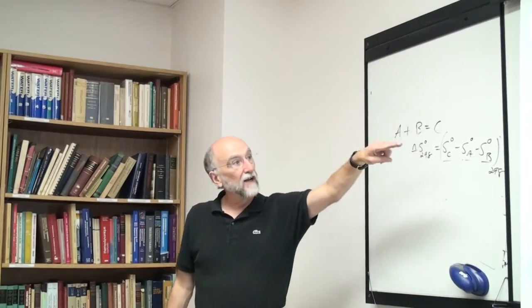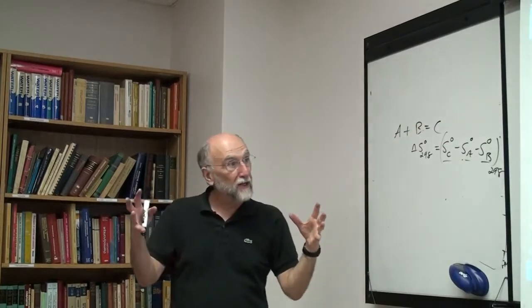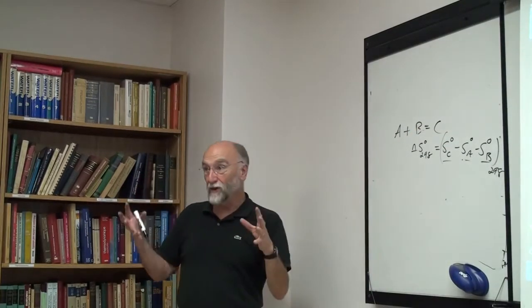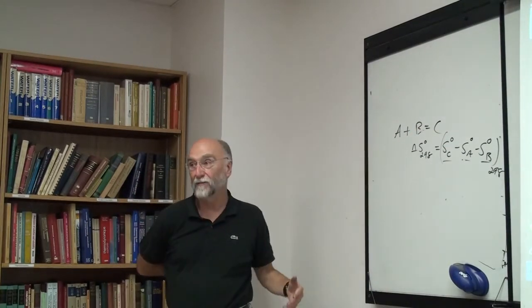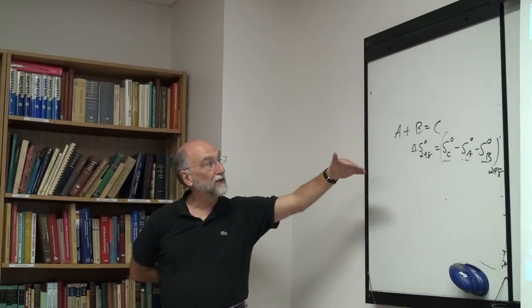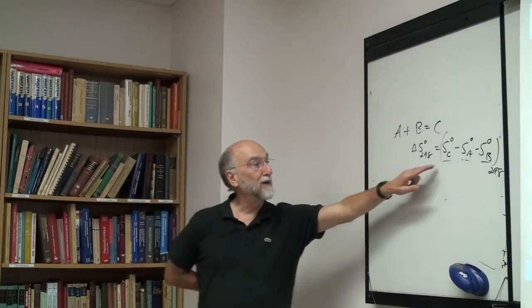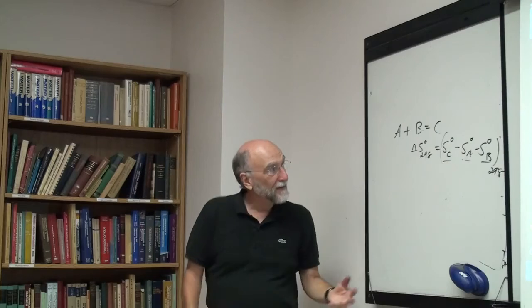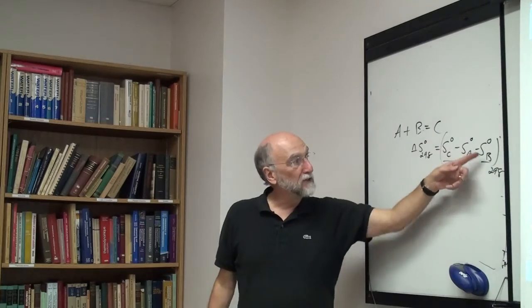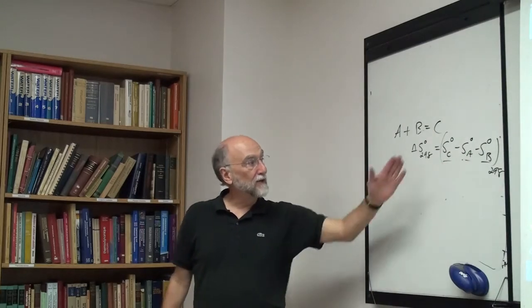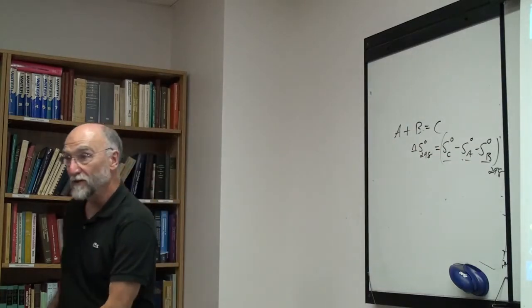And unlike the second law method, well, okay, it's sort of similar. The reaction isn't taking place, but at least you have to establish equilibrium. Here you don't even have to establish an equilibrium. The reaction never occurs, nor do we even establish an equilibrium. A, B, and C never have to come together. I just measure individual experiments on the three materials, and that gives me the ΔS of the reaction. So that's the third law method.